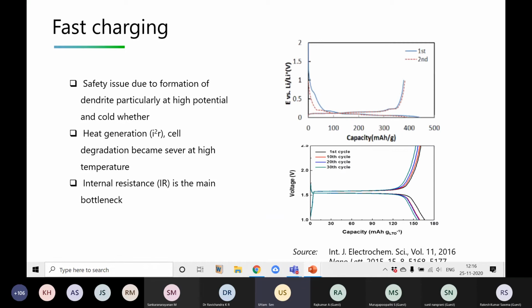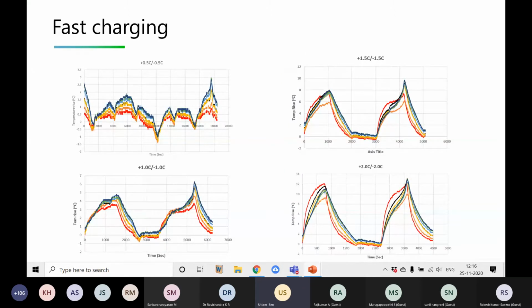Yeah. So now I will show you how fast charge is going to play, how temperature is going to be the bottleneck for fast charging or fast discharging. Okay. So we have done a test in which we charged a cell at different rates, starting at 0.5 C charge and discharge to 2 C charge and discharge, and we measured the temperature at different positions.